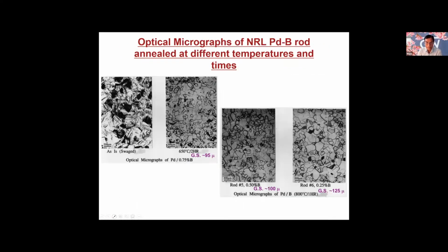Moving forward, this is a palladium boron. Now this is an as-swaged, meaning after melting we swaged it, and this is as-swaged material. This is again annealed at 650 degrees centigrade for 2 hours, and grain size roughly 95. This material is 0.75 boron. This is a 0.5 boron, and this is a 0.25 boron. And again, here the grain sizes are 95, 100, and 125 micron.